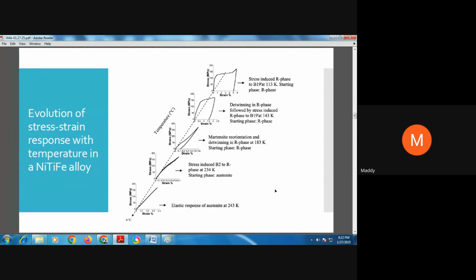This is taken from data that I researched on a material called NiTi-Fe a few years back. If we start with the austenitic phase, at the bottom end of the phase, there's a typo here. This is all in Kelvin. The 0 degrees centigrade you can ignore. If you start in the austenitic phase, when you apply stress, you get pretty much the elastic response of austenite, just like any other material.